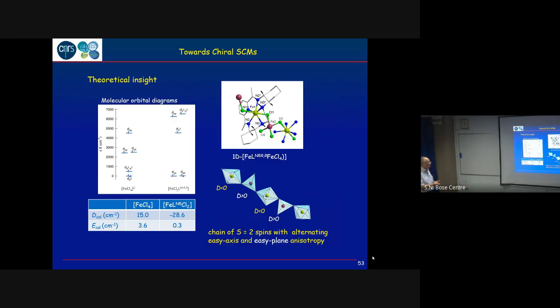And the reason for such a large anisotropy is in this energy diagram of the d orbitals. What happens in this system is that the ligand field in the apical position is getting very big. And this stabilizes all the orbitals that have a Z component. So these two orbitals come down in energy, like the Z2, and this one goes up. So we have the strong negative contribution coming from these two orbitals involved in the first excited state, but the subsequent excited states involve orbitals that are very high in energy. So the positive contribution is very small. And so here we have a system that has a large negative anisotropy because the positive contribution is just small.